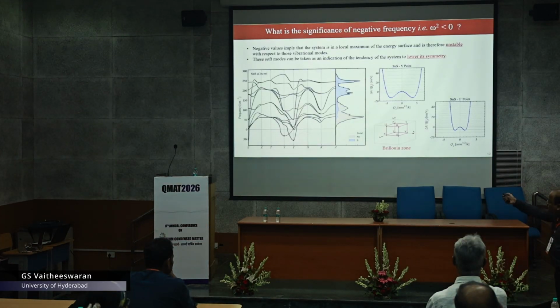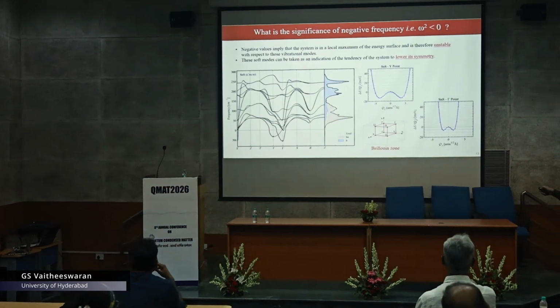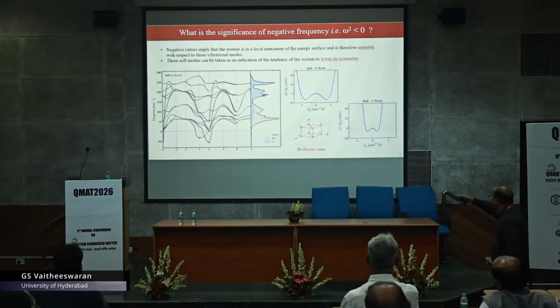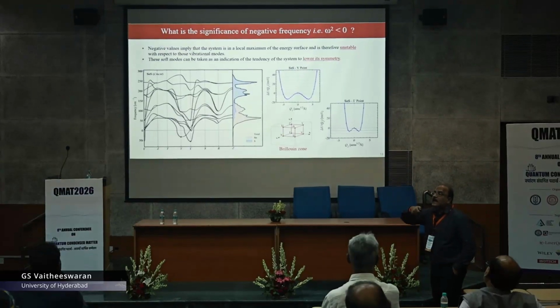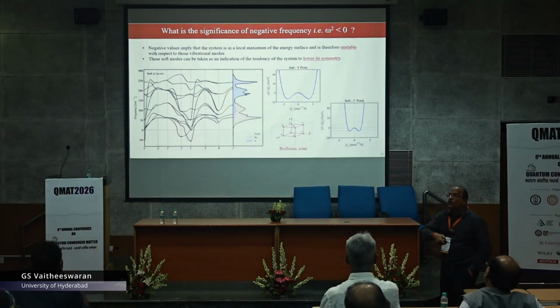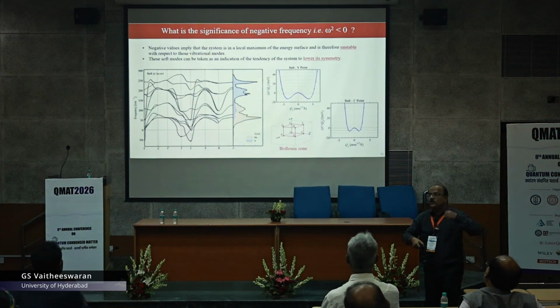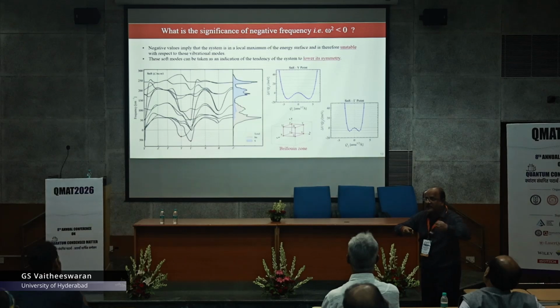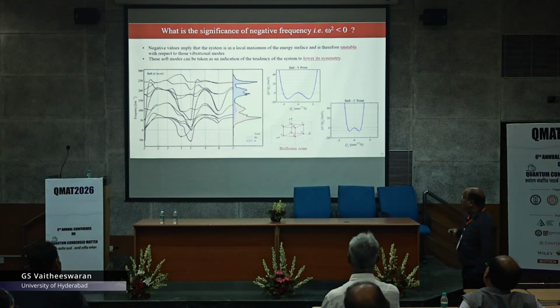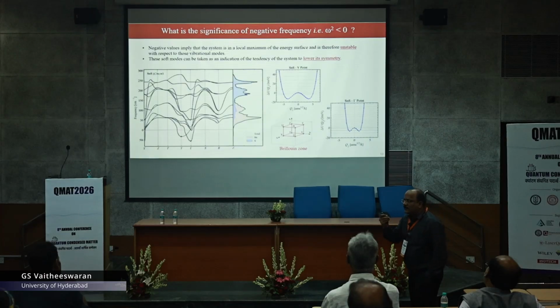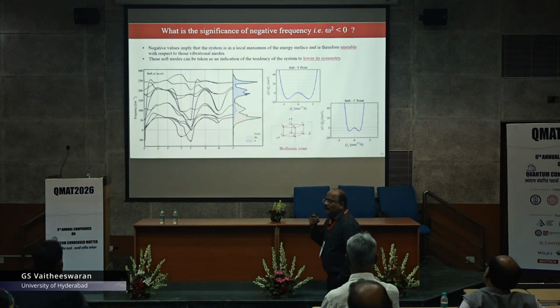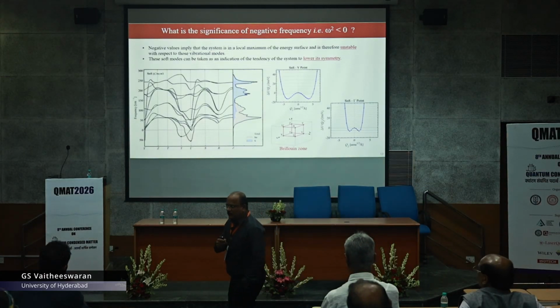So here, when you try to freeze these particular phonon frequencies which are imaginary, then we do get a nice double well like thing, and then eventually you can get another space group, which is purely a displacive transformation from solid to solid, from one particular space group to another particular space group. So this is one of the approaches which we followed, to try to shed some light on the real space group of the system.